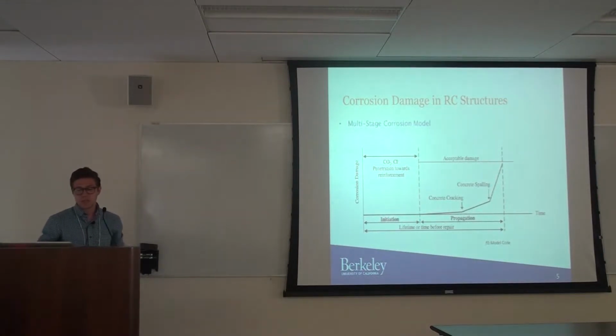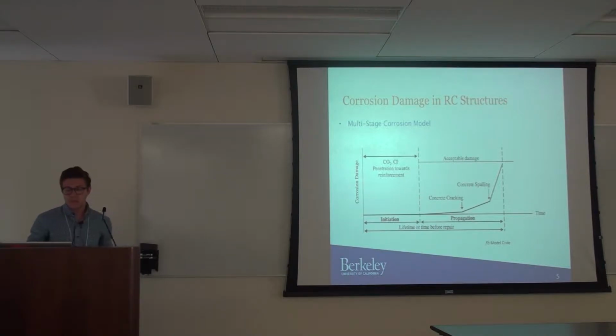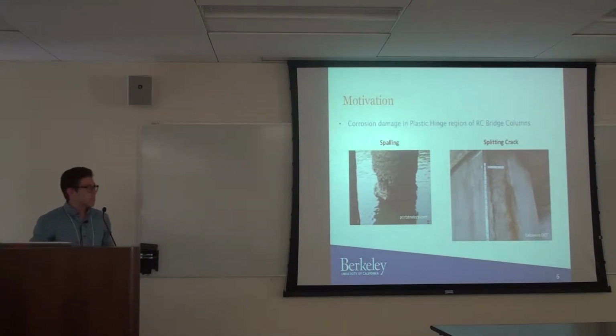But when you have penetration of carbon dioxide and chlorides, you lose that passive film layer, and that allows corrosion to begin. Then we'll see a slow increase in damage before the concrete cracks, but once cracks open up, much more of the oxygen and chlorides can come into the steel, and we see a lot more increase in damage. And once the concrete spalls, we're approaching that acceptable damage limit and approaching the end of lifetime for that column.